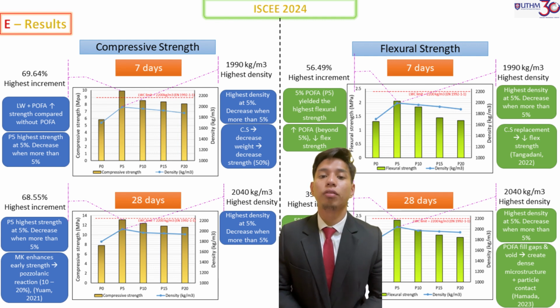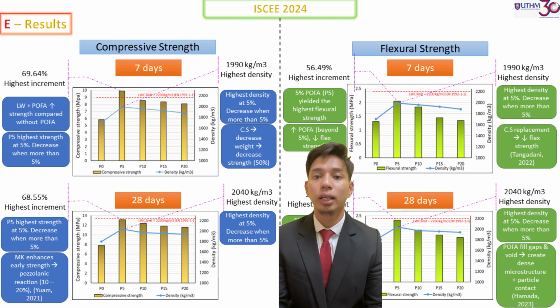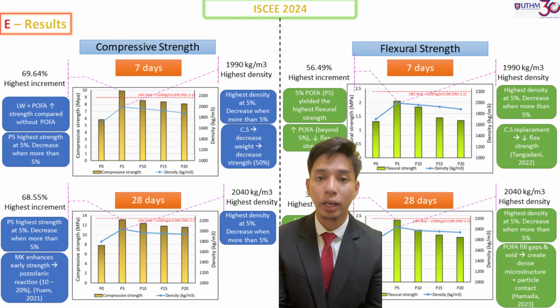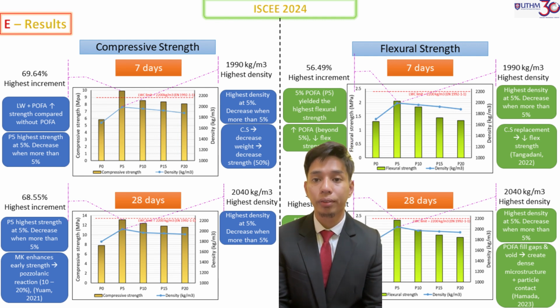So this is the result for the compressive strength. We can see that the highest compressive strength at 7 days belongs to the P5, with a 69.64% increment from the P0. Lightweight concrete plus POFA will increase the strength compared to the lightweight concrete without POFA.